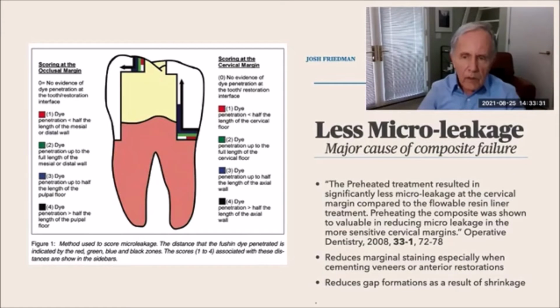So here we're looking at a study by Wagner and others where they wanted to find out more about microleakage. And what they did was they took 3 different extracted teeth, and these were 3 different conditions in extracted teeth. So the first condition was they put in a flowable liner and cured it in layers, 2-millimeter layers, and that's condition number 1. Second condition was they used no flowable liner, cured it in layers, and that's condition number 2. Condition number 3 was when they used a warm composite with no flowable liners.